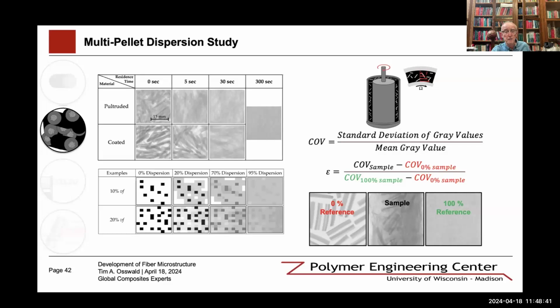So by looking at the color differences between them, doing an image analysis and finding the coefficient of variance between the different images, we can then determine the dispersion factor, which is that epsilon on the lower right-hand corner. So a reference sample, for example, you can see is 0% dispersion. So we match that reference sample as 0% dispersion all the way to the completely dispersed value, and from that we can determine the dispersion of the fibers using the coefficient of variance. So using the actual images or the X-ray images, we can then assess dispersion in different samples.